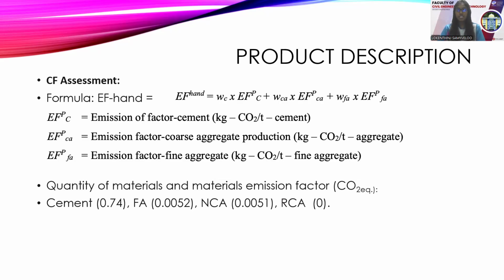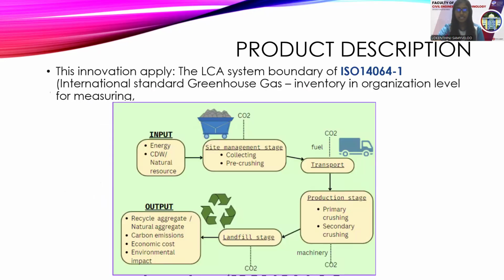The fourth, CF assessment, which is the carbon footprint formula: EF equals WC times EFPC plus WCA times EFPCA plus WFA times EFPFA. This is to calculate the carbon emission overall in the laboratory, from quantity of materials and materials emission factor, which is CO2. For cement we use a total of 0.74, fine aggregate 0.0052, natural coarse aggregate 0.0051, and recycled coarse aggregate, RCA, is 0. Next, product description. This is the diagram.